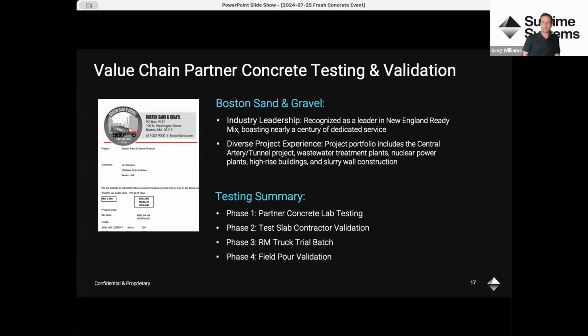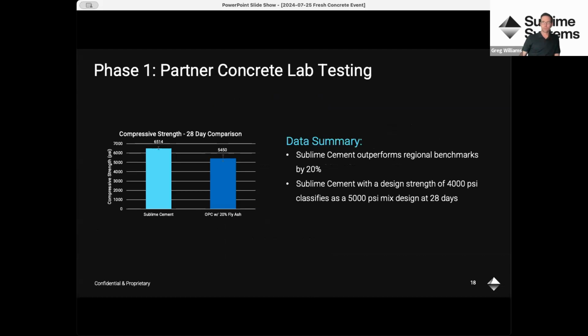And we went through a 4-phase material validation process with them. So starting with letting the partner test the material in their lab, they took their typical 4,000 PSI mix. It's a mix of about 80% Portland cement, 20% fly ash. They basically did a 1-for-1 swap, replaced all the cementitious material in that mix with Sublime Cement, and then tested it in their lab. They saw that at 28 days, we outperformed their benchmark mix by about 20%.